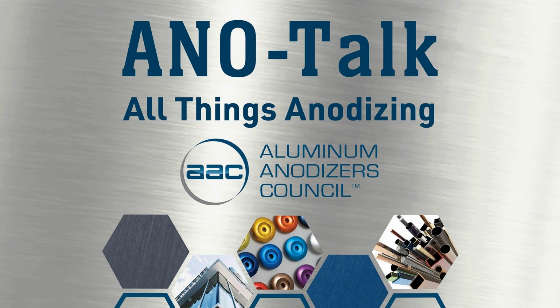Pulse anodizing is just a way to, instead of having a direct current, where you're applying a certain amount of current, 15 amps per square foot, and you continue using that the whole time, or you're applying 15 volts the whole time. By pulse anodizing, you start changing the current to different values. So it's kind of like ramping. A lot of people do ramping.